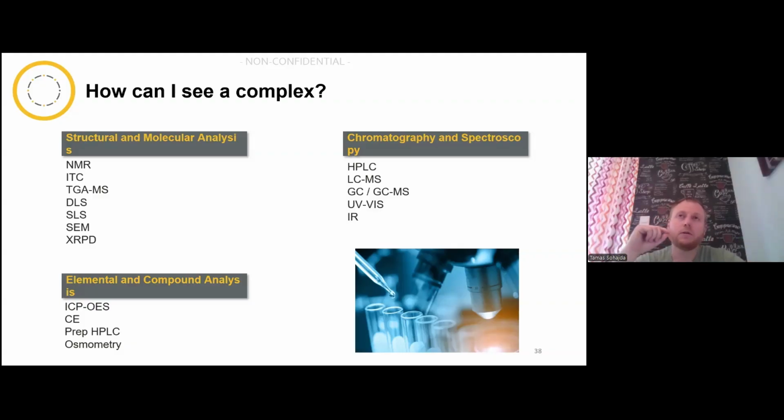You cannot distinguish the free active and the complexed active and say that, okay, 25% of my active is still free. But you can see how much it's shifted from the free towards a hypothetical full complexation, and you can calculate the complexation rate.